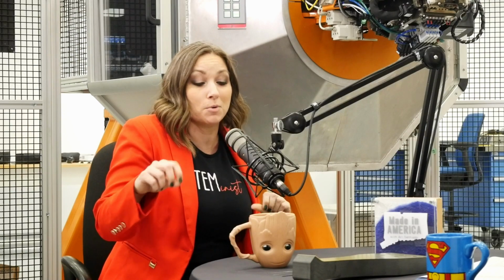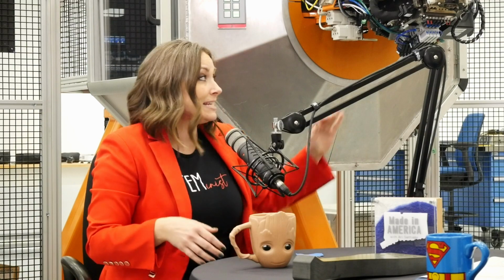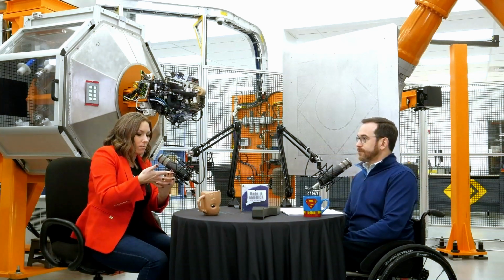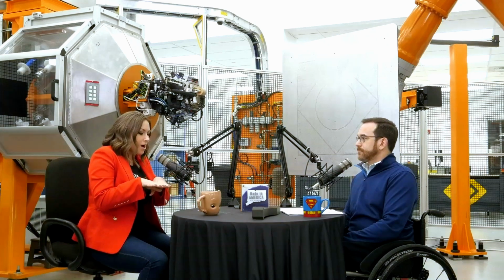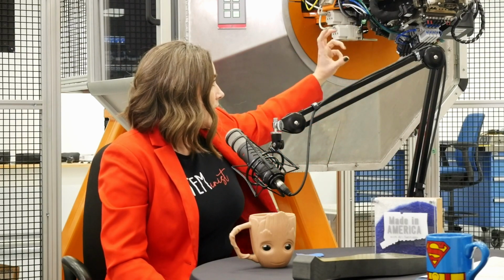They're called tows, and they're layers of composite material, pre-pregnated carbon fiber and polymer material. There's 8 of them that come out of this little roll there, and most people are familiar with carbon fiber woven composites, right? You see a lot of them in automotive, and this technology is not woven. So these tows are aligned adjacent to each other. They're heated and compressed along that complex geometry. And then this gantry system will move in different angles according to what the design requires. So again, we're building three-dimensional complex geometries of aircraft components.